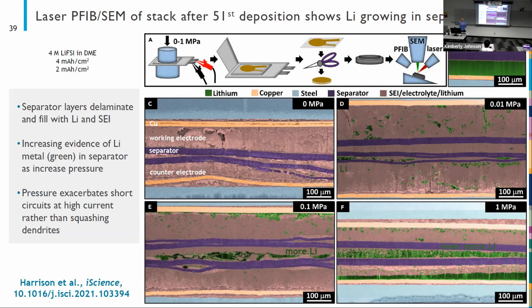The one reason I think that it doesn't is because we see that residual strain, right? So we've essentially cold worked the material by putting it under pressure, and then it's trapped in that strain state. But you're right that it could change by the time we actually look at it and open up the battery. It's a really good point.